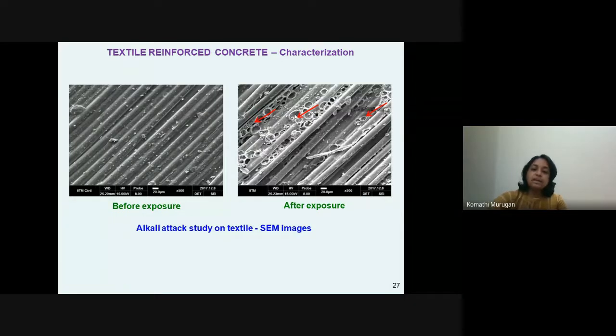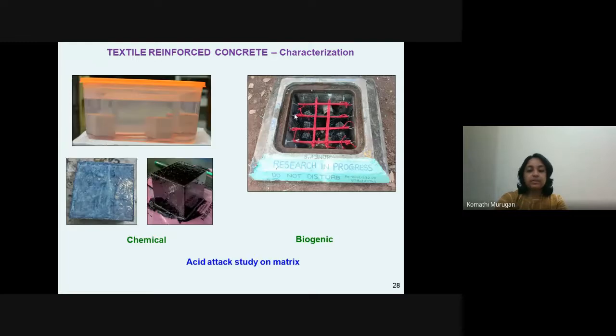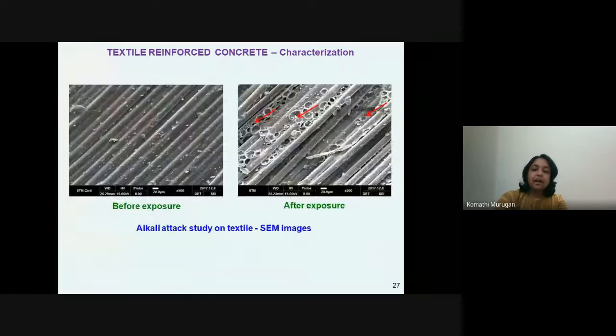So what we do is study the deterioration of the textiles on exposure to the alkali environment, and accordingly we are now working on engineering the matrix in such a way that the glass dissolution, what we call the alkali silica reaction, is very much reduced. So that is on the alkali attack. This is on the textile.